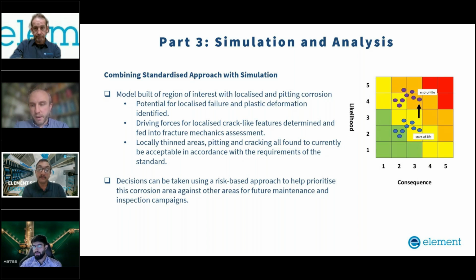Through fracture mechanics type assessments in the fitness for service procedures, through iterations on our numerical simulations to see what the effects on the global response of the pipework was to increased levels of corrosion and cracking, we were able to identify what the driving forces of those damages were, and also compare them to the resistance of the material and the structure to be able to withstand those areas of damage.